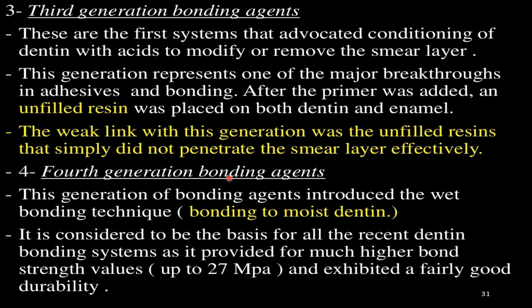Fourth-generation bonding agents introduced the wet bonding technique, bonding to moist dentin. It is considered the basis for all recent dentin bonding systems as it provided much higher bond strength values, up to 27 MPa, and exhibited fairly good durability.